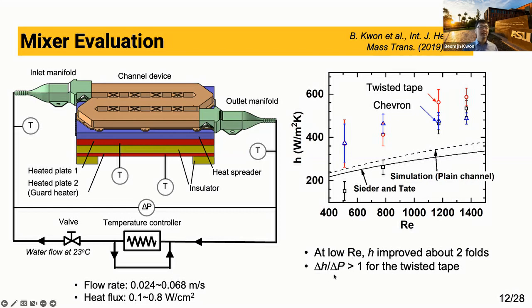And we also estimated the increase of convection coefficient per increase of pressure drop, and it was greater than 1 for the twisted tape. But for the chevron tape mixer, the pressure drop was less, but the improvement was slightly less than those for the twisted tape. So it was almost close to 1 for the chevron mixer. So I think this example demonstrates the usefulness of 3D printing for the cold plate.